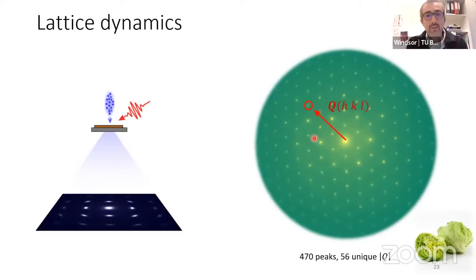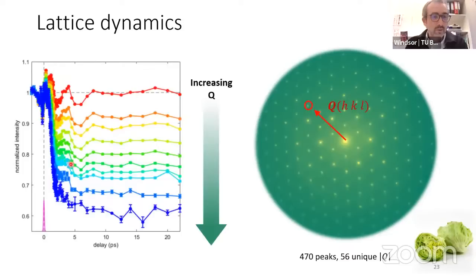So for now, I'm just showing how these peaks weaken in intensity. And this is what is shown here. This is for increasing distance from the center, and this makes a lot of sense to anybody who is familiar with this technique, because as you go away from the center, you have a stronger Debye-Waller response. Now, this picture here is not the newest analysis of these data, but everything here is qualitatively very, very correct. There's a bit more cleanup that needed to be done here. So we have these wiggles that we see here, and we have the more obvious drop on very fast timescales happening at about a picosecond. Time zero here is a bit shifted.